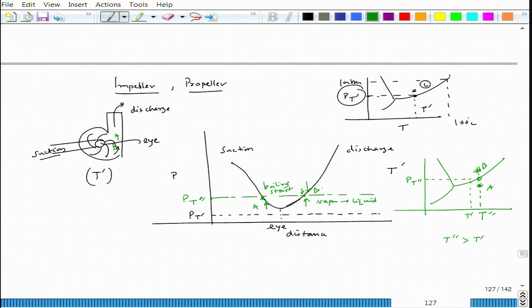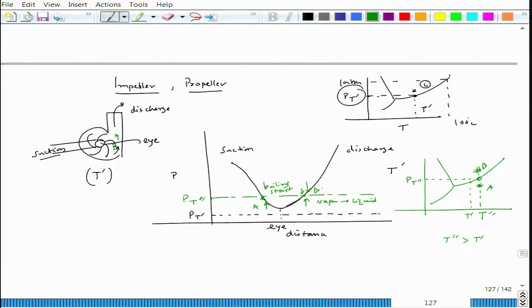So, that way this cavitation damage happens in a moving object, wherever a fluid is taken with the particular moving object. So, this is the situation in the case of an impeller or a normal household centrifugal pump, okay. This is one such instance where cavitation damage happens over the impeller. In fact, the impeller blades can be broken into small pieces. And another interesting part which I missed: when the bubble collapses, it actually leads to a shock wave, okay. So, that shock wave would also lead to damage to the material, and this bubble collapse can also lead to a sound.